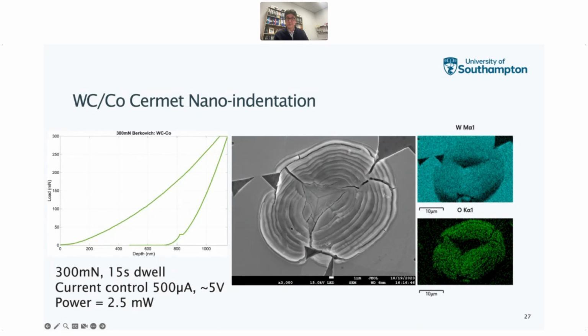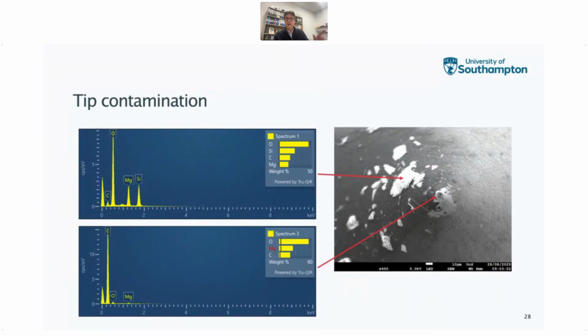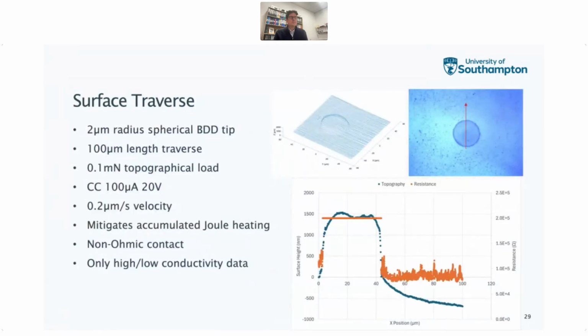So this is a little bit challenging for us now. How do we mitigate against this? And so there's a couple of things we can do. Before I get onto that, if you do start doing this, you then start running into tip contamination, because that oxide is often then adhering to your tip, and you have to start deploying strategies for removing it. I'm not going to go too much into that today, but essentially to say that you want to avoid this really is the best strategy, I think. Couple of things we can try then.